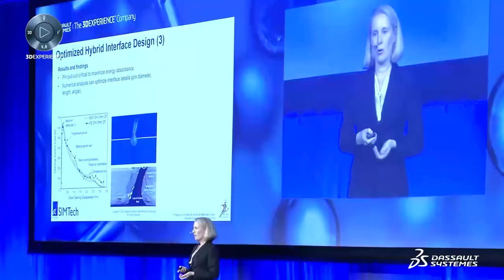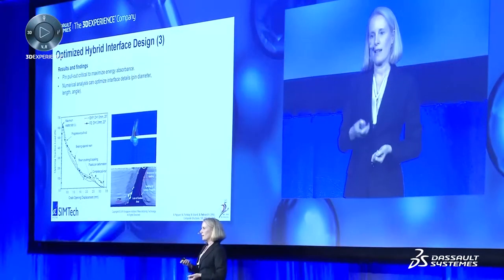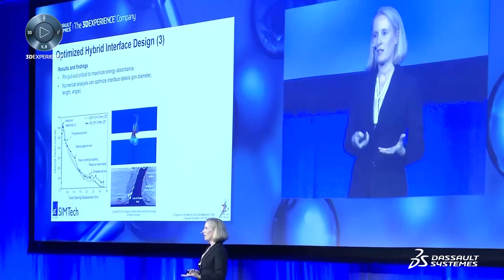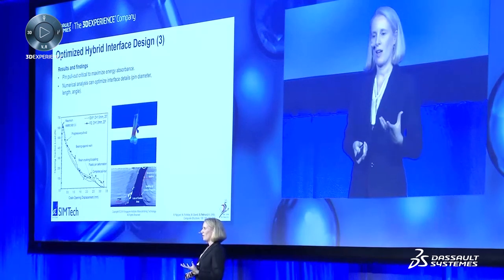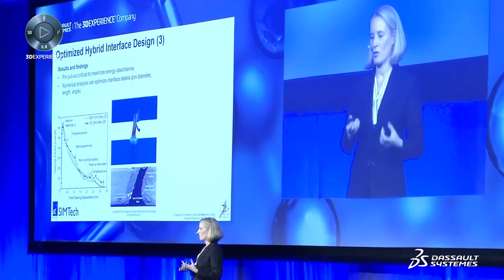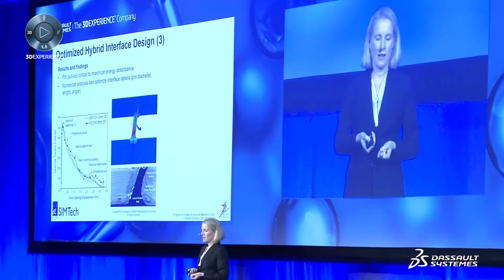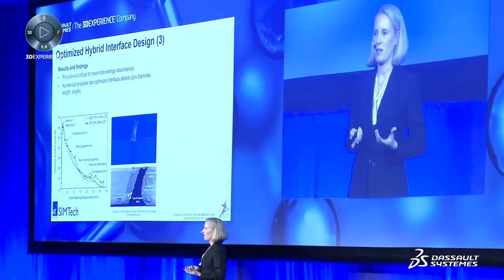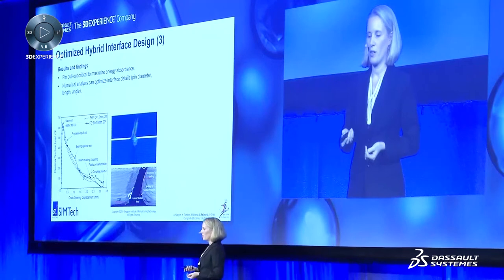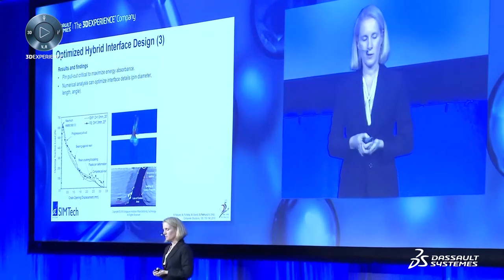Alex. He created a full fidelity model with an angled pin pulling out of a composite, looking at the stresses in the pin, having ductile failure of the pin, but also having composite failure included, so he could see what's happening in the composite at the same time. And that was all experimentally validated through tomography, but also through the load displacement curves.